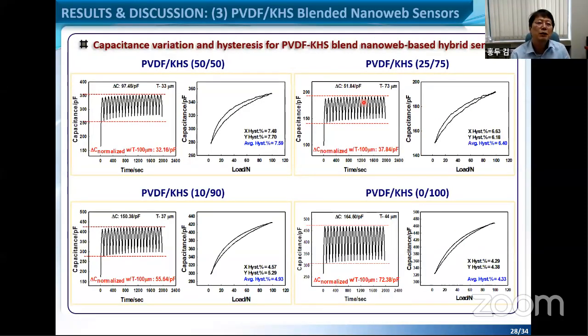So let's move on to the PVDF and KHS blended system. It's very similar to the previous result. In this case, just for the capacitance variation, we can look at the 50% to the pure KH case only. As you see there, hysteresis is about 7 to 8%, and the capacitance change is about 30 picofarad. It's not that bad. The only problem is some kind of creeping behavior, but we have to think about how to improve this one.